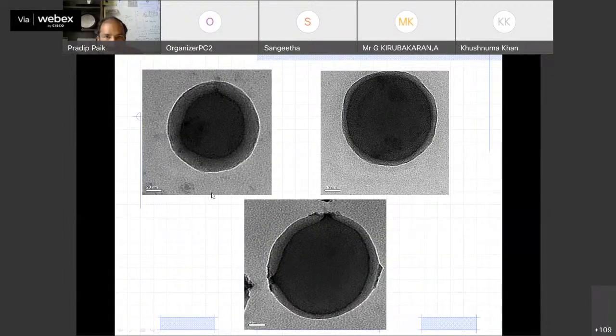Now you see how it looks in the high resolution TEM. This is the capsules. Shell thickness is 20 nanometers, and the hollow cores are filled up with liquid. Now you see this core-shell polymer nanoparticle, where this is the core, almost 5 to 10 nanometers. So you can vary, and it is full with liquid or, let's say, empty. In these cases, the particles are, let's say, 100 to 150 nanometers.